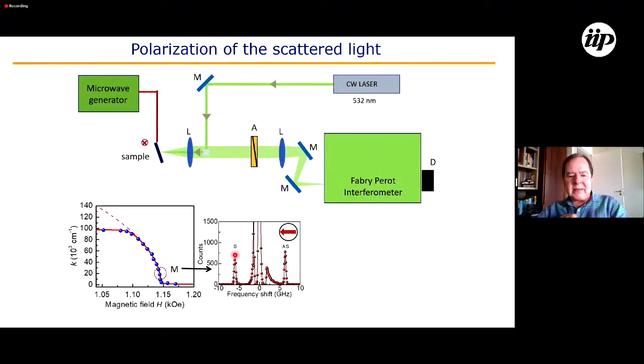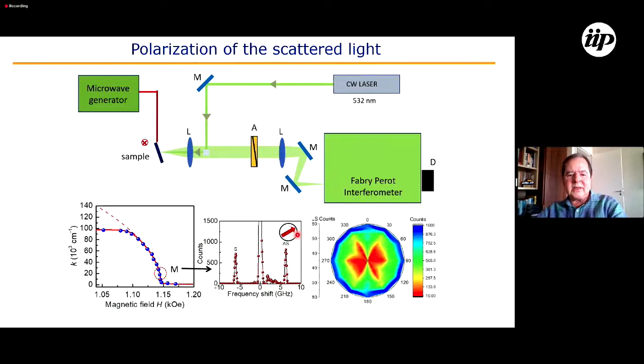So we look at the intensity of this Stokes and anti-Stokes scattering with the angle of the analyzer. It practically doesn't change. So if we make a radial plot of the intensity, we have circular polarization. This is expected because magnons correspond to the precession of the spins, and magnons produce circularly polarized light.